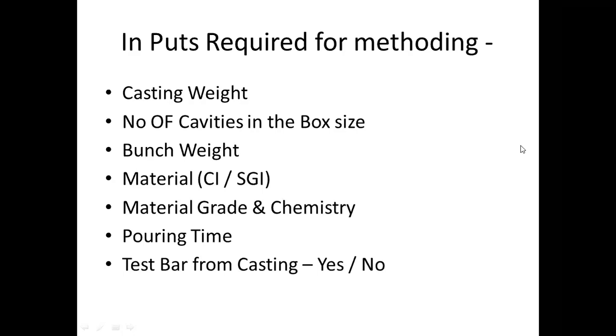Input required will be casting weight, number of cavities per box, bunch weight, material, cast iron, or grade and chemistry. Pouring time we are going to calculate. Test bar from casting, yes or no. Many times for critical castings, considering the field use, people like Parker or John Deere ask for the test bar from the casting. That also needs to be taken into account while doing risering.